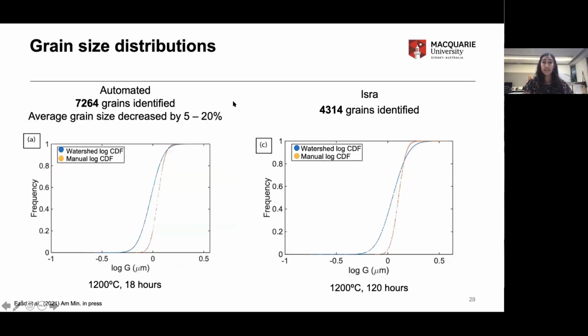So the grain size distributions. If you remember back to the beginning of my talk, I mentioned that I really needed log normal distributions to ensure that I had normal grain growth occurring. The automated technique actually found 68% more grains, considering that I measured 8 fewer images. I only found 4,314 grains.